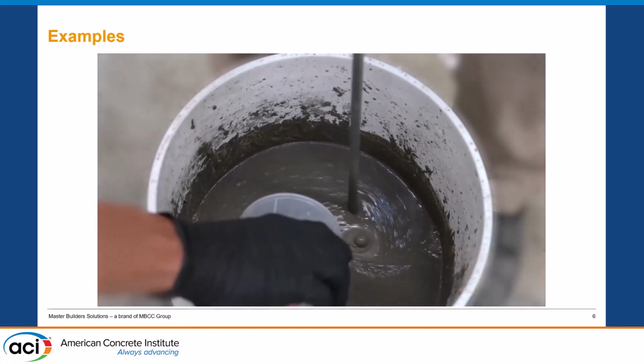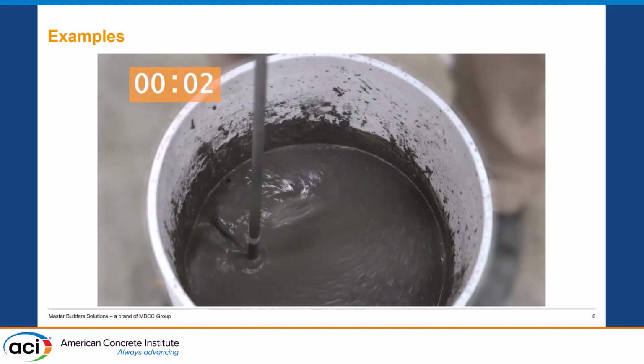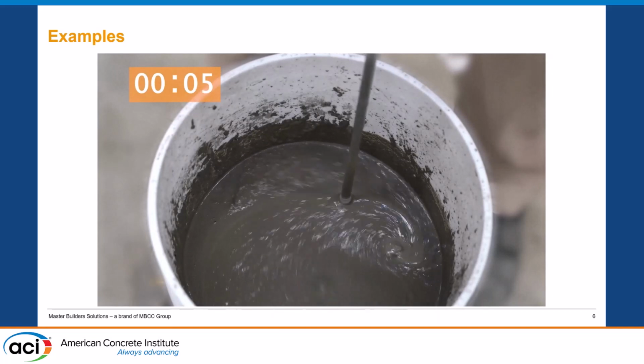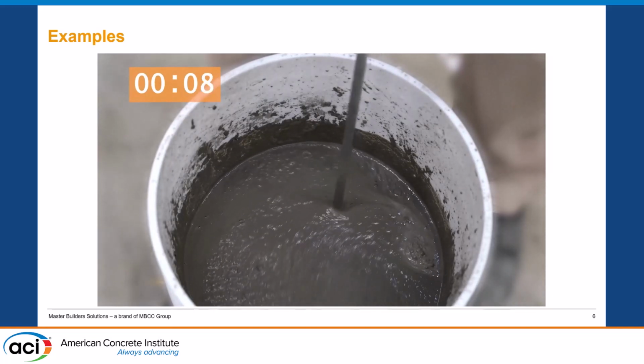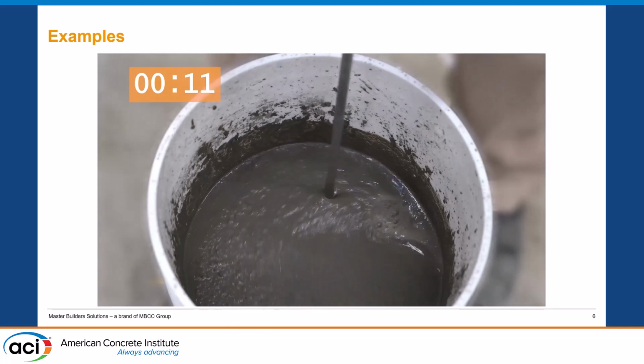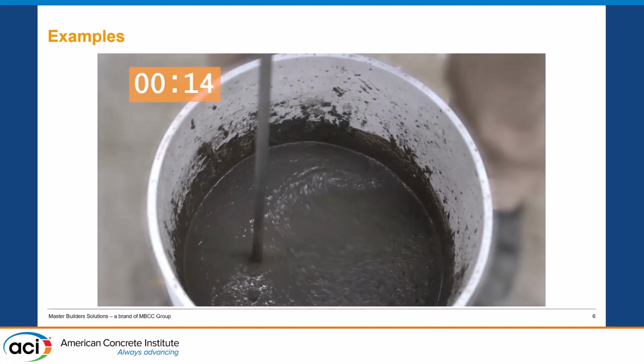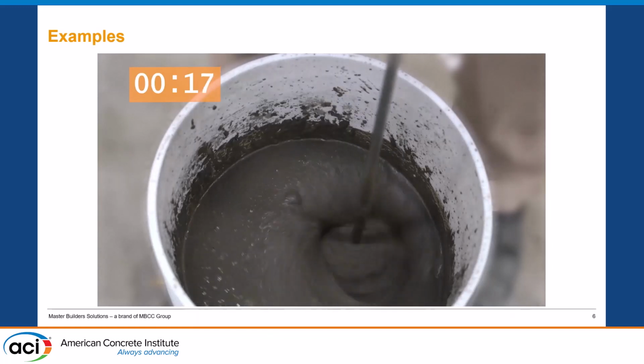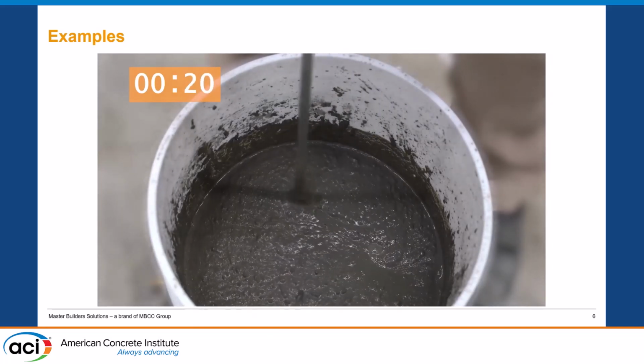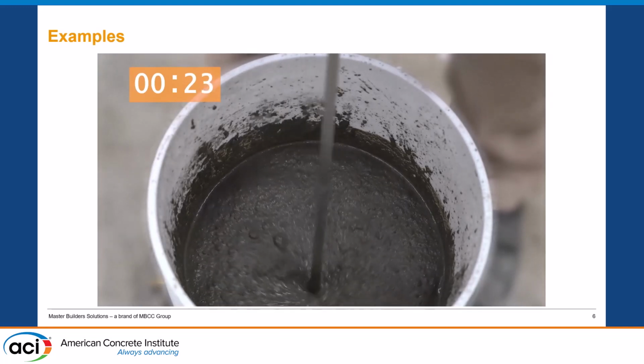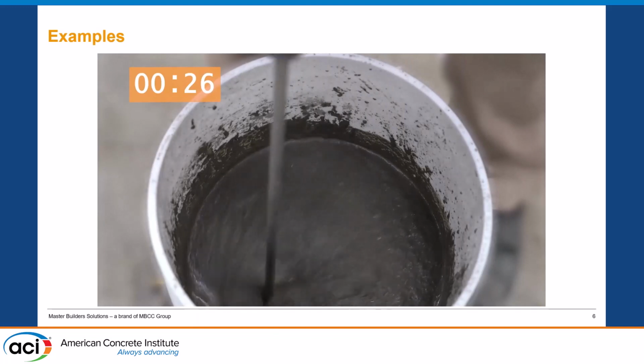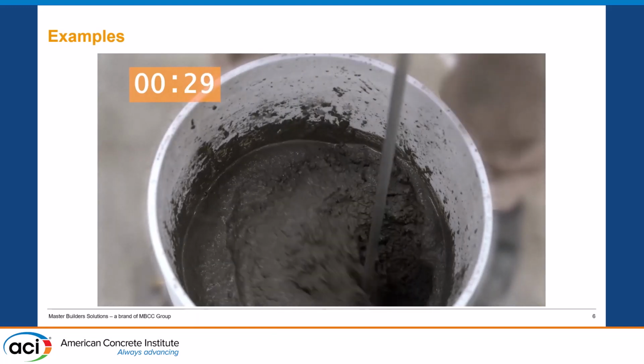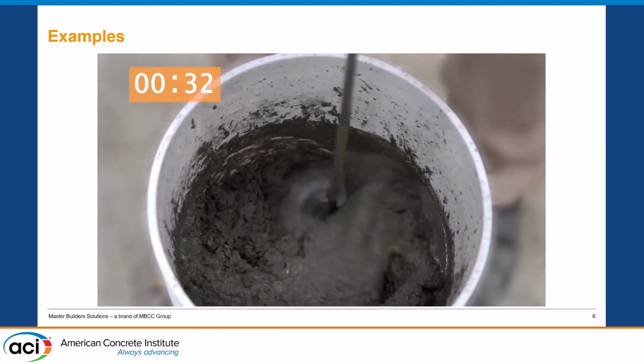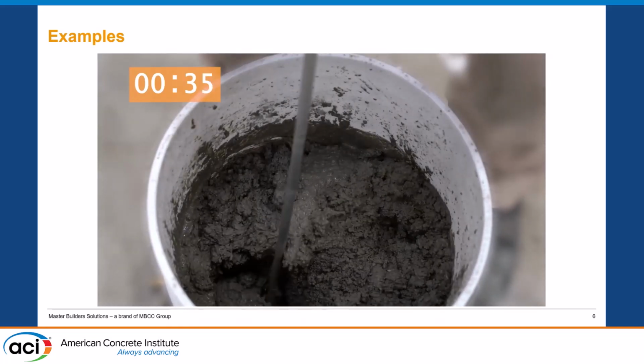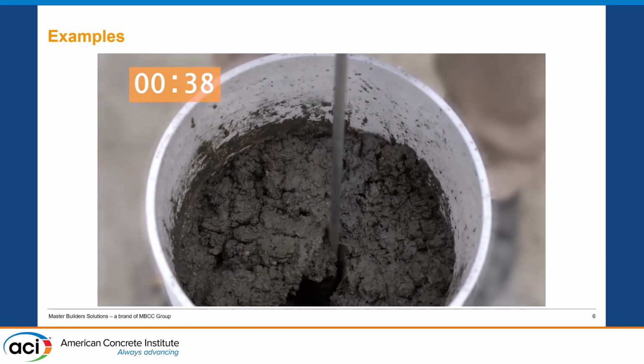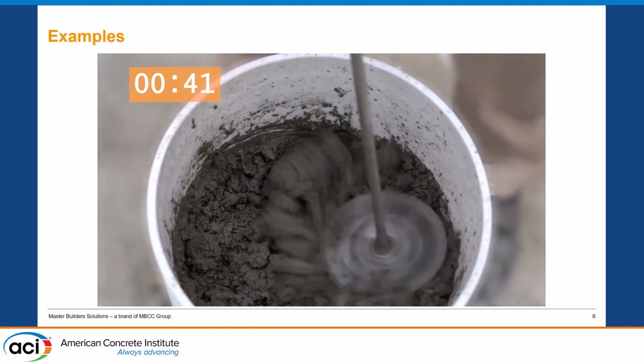The admixture is then added, as you can see here. The admixture is a super absorbent polymer, but of a special kind, not necessarily the super absorbent polymer you will find in baby diapers or in other hygiene products. When added to the concrete, it reacts partly because also of the high alkalinity of the mix, and it draws all the water out of the system, and basically this is how you start forming dry aggregate in a matter of seconds. As you can see here, we only lapsed around 40 seconds, and something that was liquid as a grout is no longer workable.